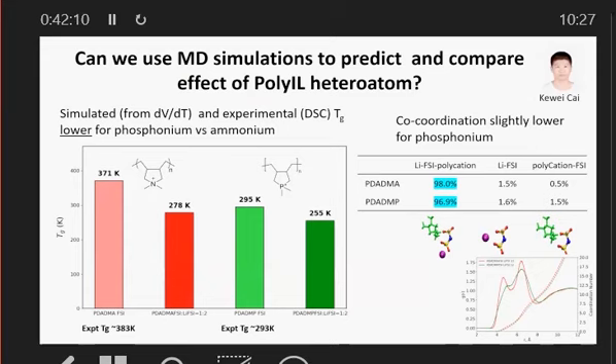We see that the ammonium versus phosphonium, definitely there is a significant decrease in TG in the pure polymer. You go from 371 to 295 K in the MD simulation. That correlates to reasonably similar values in experiment, 383 to approximately 293 K in DSC experiments. So that was nice.